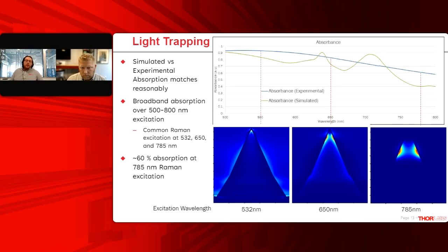Yeah, so for this modeling, we did have to simplify it just due to computational constraints. In this case, we have a single nanopillar, and we optimized the height and the width of the pillar, as well as the gold thickness based on our experimentation. When we did optimize that size, we found that this was really optimized for field enhancement in the 785 nanometer region. So in this case, we were modeling around 10 to the 4th electric field strength for 785 nanometers. However, this value will change depending on the wavelength that's chosen.